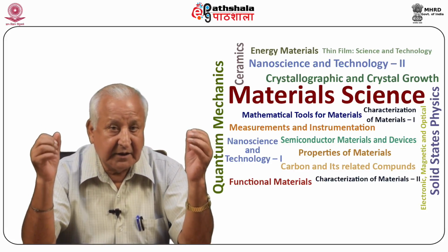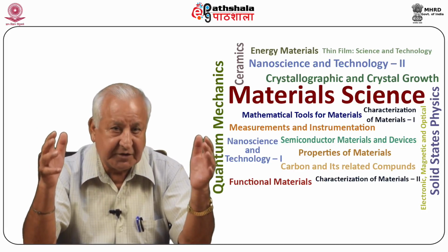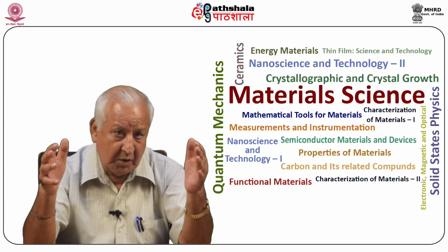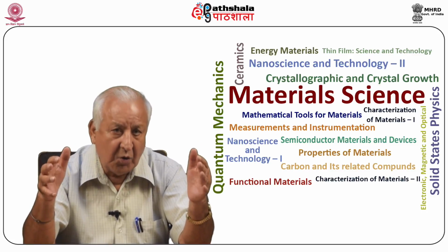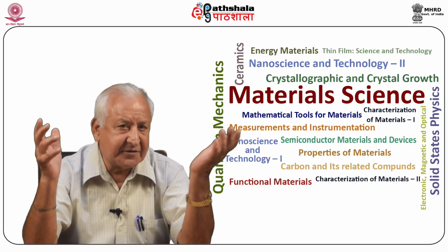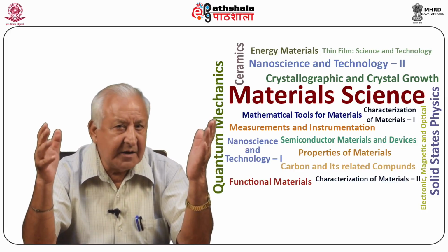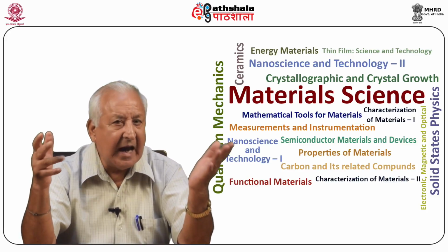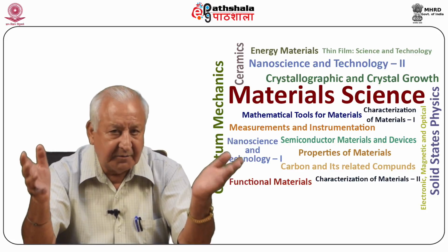In a similar way, the driving force for the growth of a crystal from vapor is determined by the degree of supersaturation, which is defined as (P minus P0) upon P0, where P is the pressure of the vapor and P subscript 0 is the vapor pressure of the solid. In spite of the fact that the lattice structure is considered as perfect, the crystal may have imperfect faces. An imperfect face is one which may consist of terraces, steps and kink sites, that is, re-entrant corners. The step covers only a part of the face.